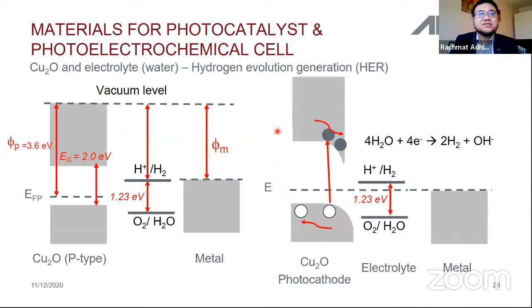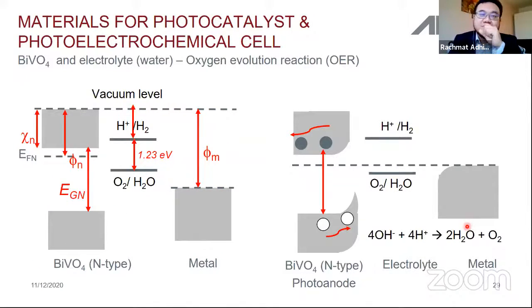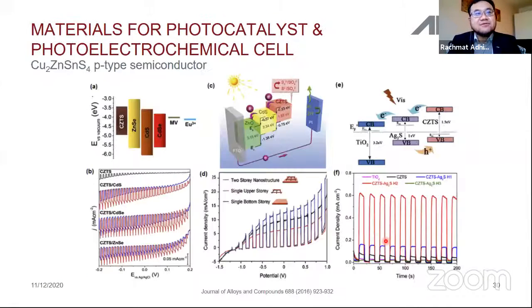At the same time, holes try to make a complete circuit going into the metal. And this is bismuth vanadate, which is really famous also for producing oxygen. Bismuth vanadate is an n-type semiconductor, and what happens here is that once the electron is excited into the conduction band, it goes there because it cannot climb, while the hole climbs to the surface between the bismuth vanadate and the electrolyte and reacts with water to produce oxygen. So it oxidizes water basically. This is one of the examples also.